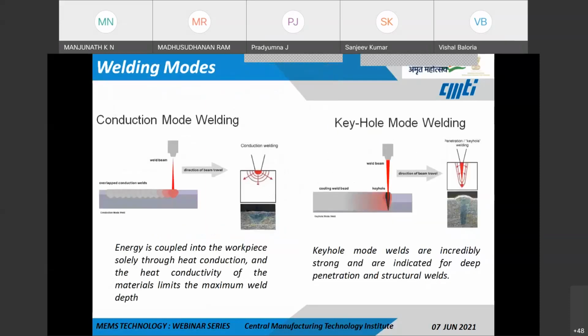So again, welding modes. There are two different modes: one is the conduction mode of welding and the other is the keyhole mode of welding. In conduction mode, the energy is coupled into the workpiece solely through heat conduction, and the heat conductivity of the material limits the maximum. We see that the weld depths are very small. So these are preferred in applications wherein aesthetic looks are very important, and they also produce a very smooth weld, and they do not require any grinding operations. Once the weld is done, it will not require any grinding operation.